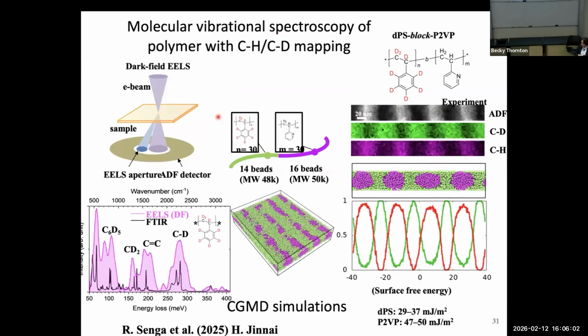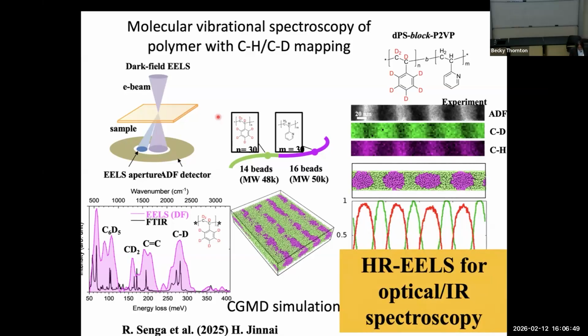And for the energy resolution, we have many different ways to go. One of the examples is that we could make some molecular labeling, and we could get information on the hydrogen isotope. If you make some heavy hydrogen that has a neutron, in this case you can get a clear map using the vibrational yield. So you could distinguish the stretch energy of CH and CD. So this is also an important direction for us to go.